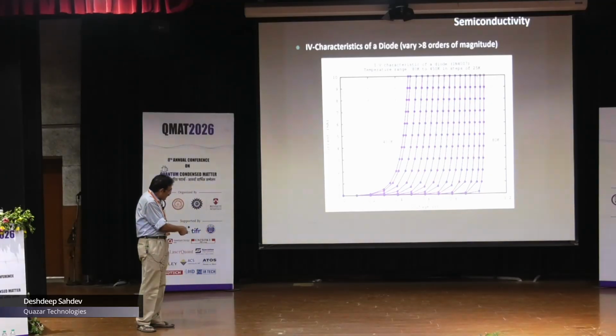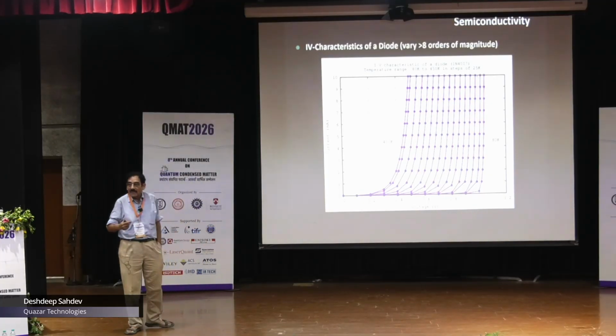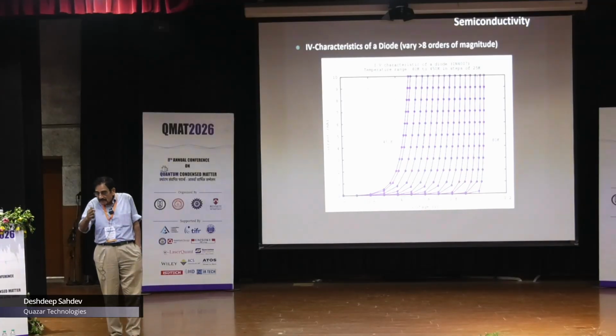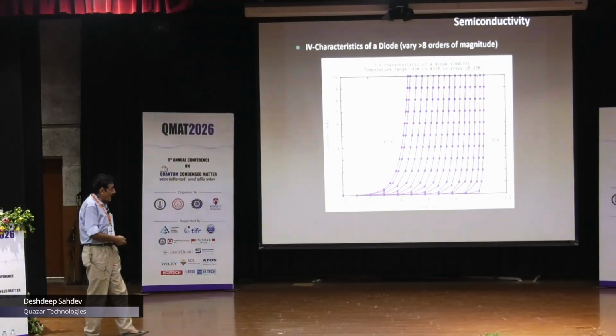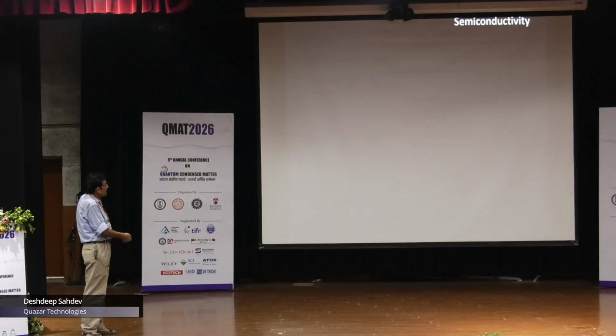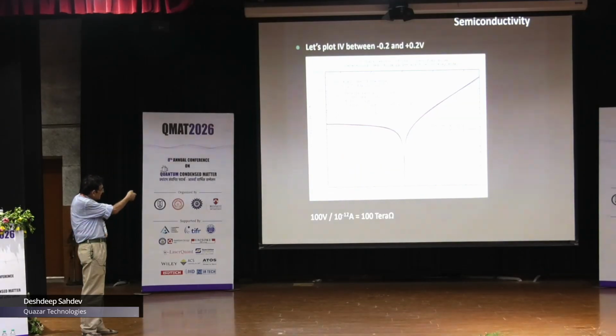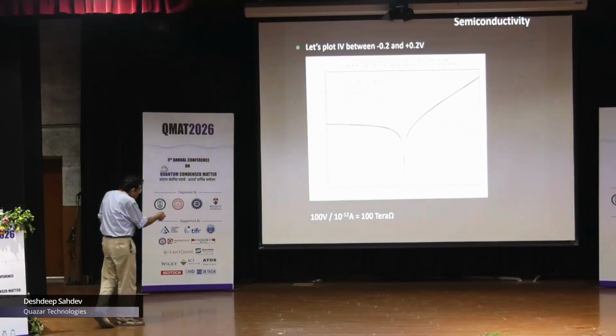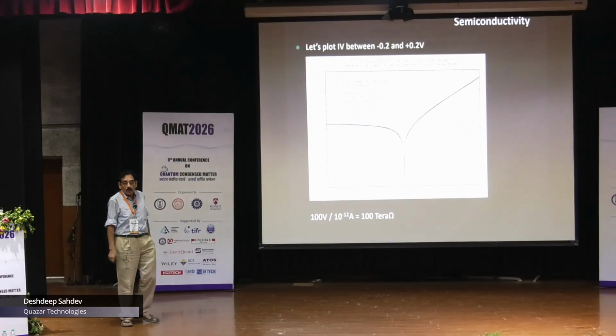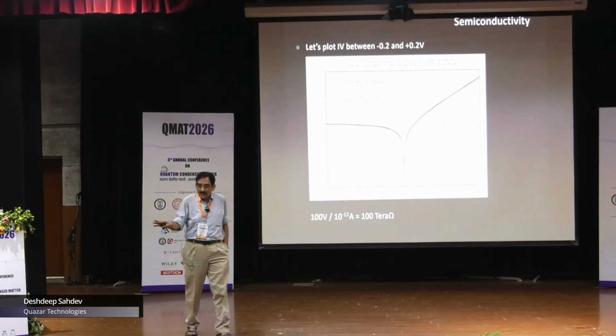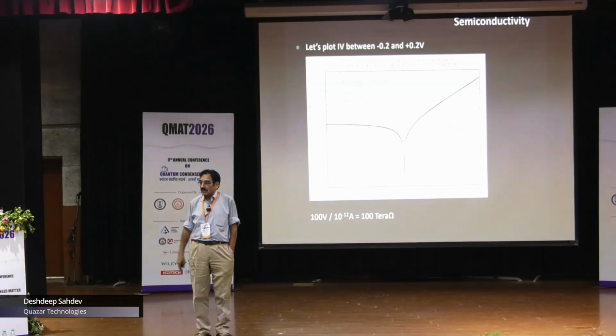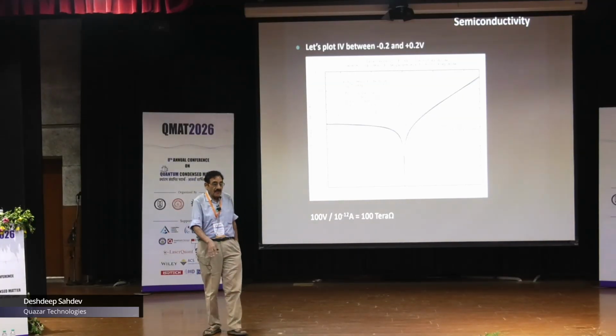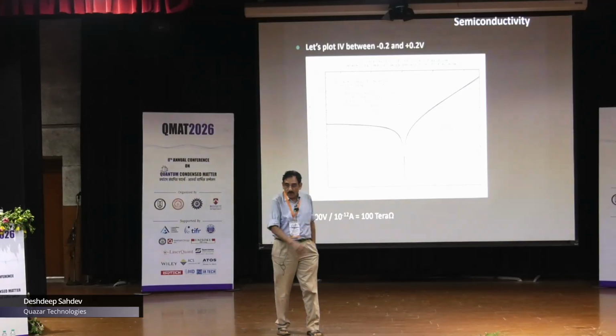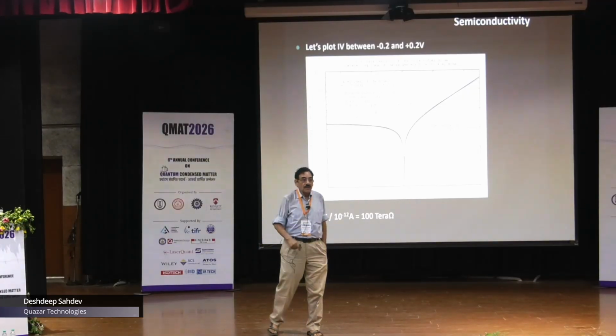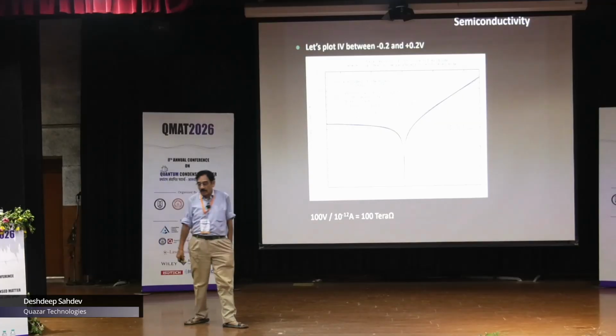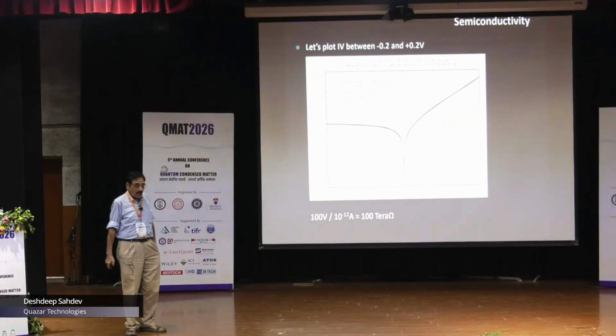Here, of course, you don't get any structure. You need something which is much, much finer. You have to be able to take steps which are 1 millivolt and be able to measure much smaller currents. So between this, we measured that. We can now measure all the way down to 1 picoampere. And now this is not Keithley or anything. This is stuff that we have built again from scratch. All the picoammeters, the source and measurement units have all been built by us, all right? And we can go down to, in fact, noise levels of as low as a few hundred femtoamperes.